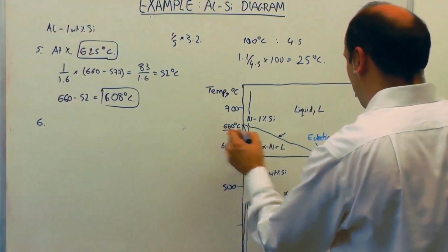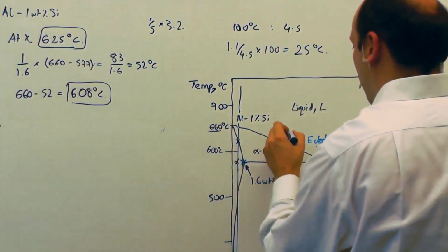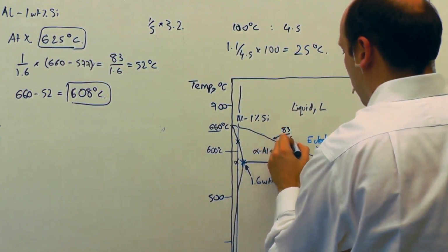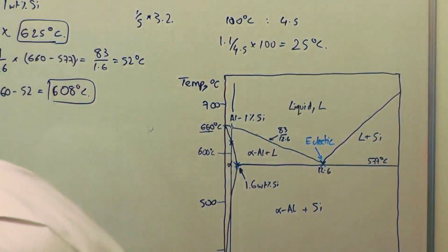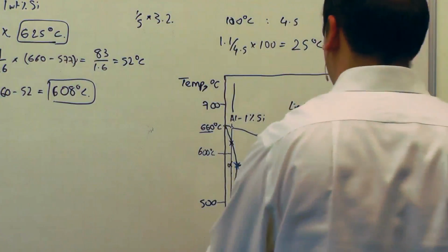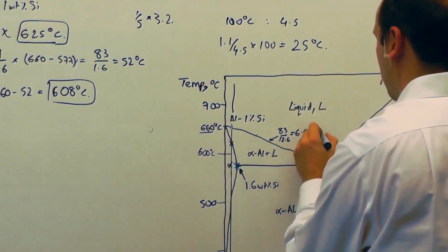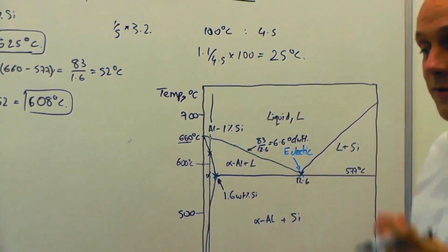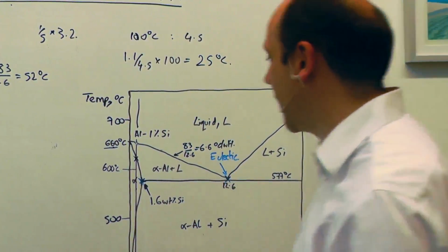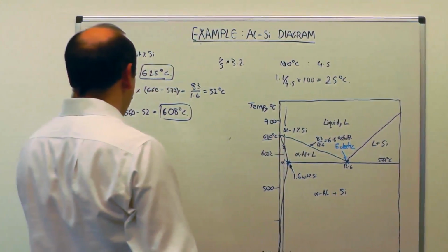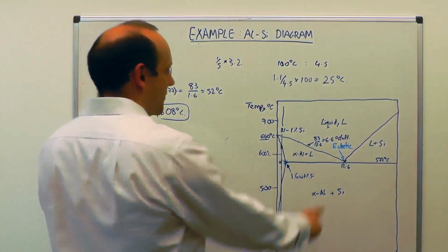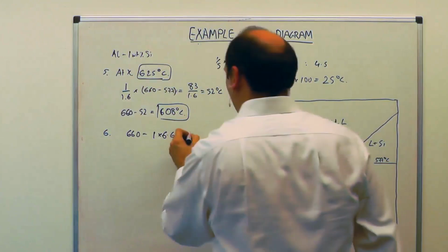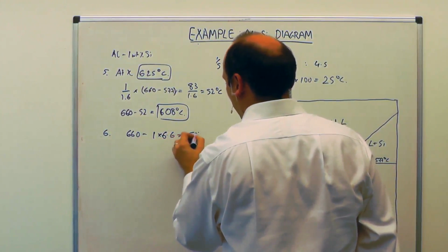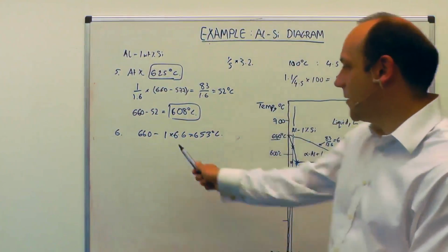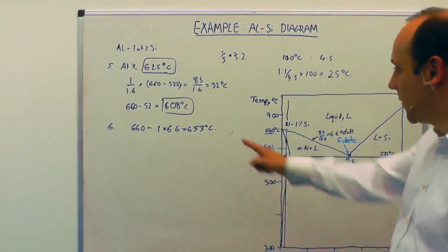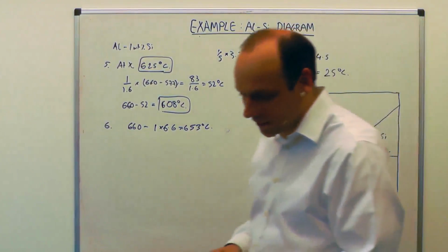If we assume this is a straight line, then it has a gradient. It declines 83 degrees, from 660 to 577, over 12.6% in weight percent. So that declines by 6.6 degrees C per weight percent. That's the gradient of that line if you assume that it's straight. So we're in an aluminium 1% silicon alloy, so it'll start to solidify when it hits that line. That's at 660 minus 1, our alloy content, times that gradient, which is 6.6. So that's at 653 degrees C, if you say that's about 7. That's when solidification will first start to occur and you'll first start to form solid.